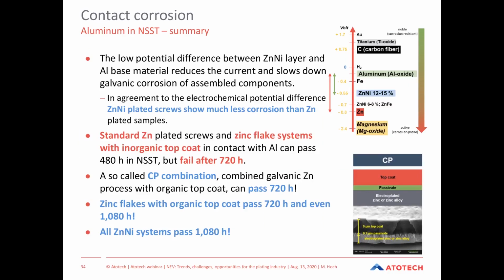So to summarize aluminium: the low potential difference between the zinc nickel layer and the aluminium base material reduces the current and slows down galvanic corrosion of assembled components. In agreement with the electrochemical potential difference, zinc nickel plated screws show much less corrosion than zinc plated screws. Again, we have this green arrow here, which is a short potential difference between the zinc nickel and the aluminium. Therefore, we get low corrosion, whereas the red arrow is a bigger potential difference between zinc and aluminium, and we get more corrosion.